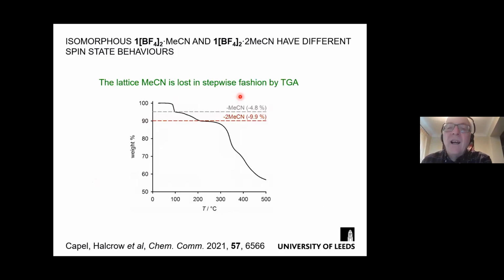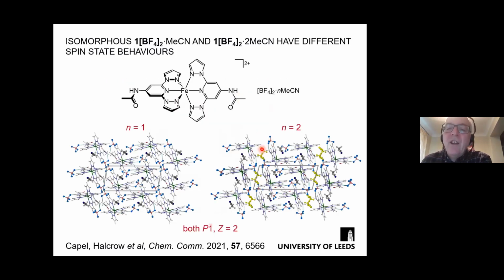Now, you can maybe understand this if I go back, just because if we have extra solvent in this lattice, then the crystal packing in this structure is denser. We have more atoms in this unit cell than we have in this unit cell. So probably there's just not enough space inside this crystal lattice to allow the structure changes with spin crossover to take place. This is a denser crystal, so kinetically, it's maybe trapped in its high spin form. That's how we understand that.